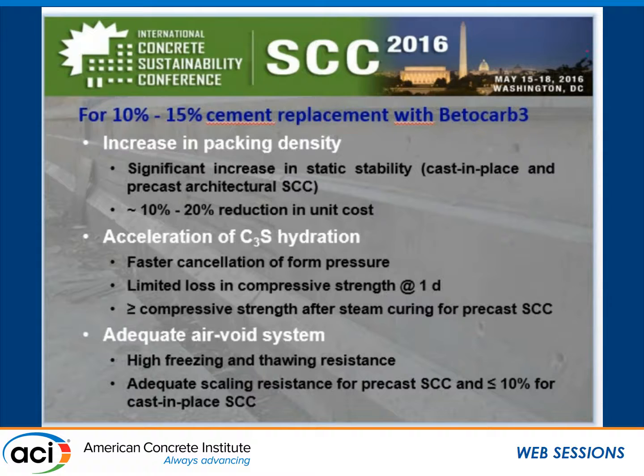In terms of durability, despite the very good air void distribution, we got excellent freeze-thaw durability, but we would not recommend this type of calcium carbonate to go above 10% when we are using it for pavements or sidewalks when the water to powder ratio is on the order of 0.42. So if we limit it to 10%, we don't think there's a problem. If your water powder ratio goes lower than that, or your cement is a type 3, then again, we don't see any problem with scaling resistance.